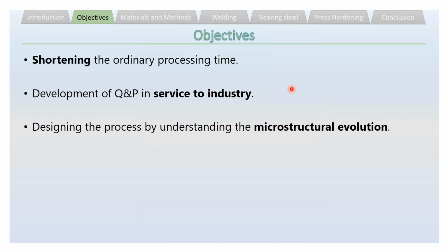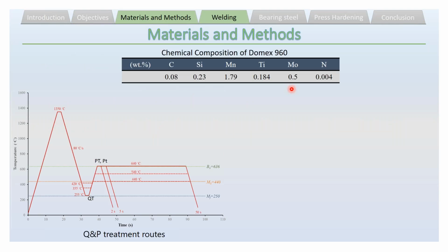The objective of all these three is shortening the ordinary processing time, developing quenching and partitioning in service to industry, and designing the process by understanding the microstructural evolution. Just very shortly, we can take a look at the results. In the first application, welding, we selected 3 quenching temperatures, 3 partitioning temperatures, and 3 partitioning times.